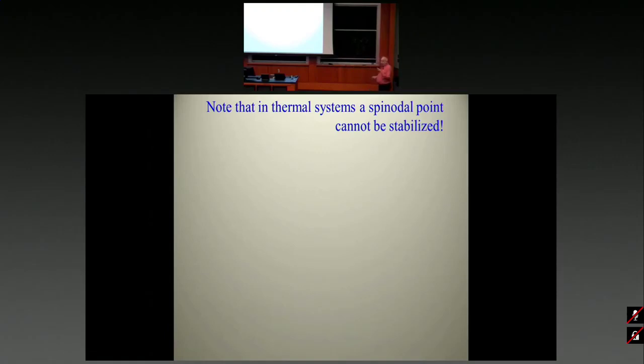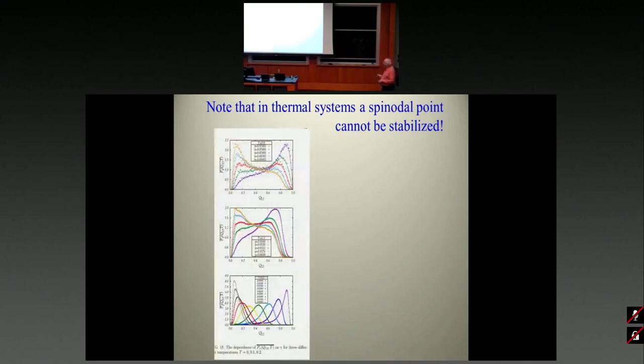So I just want to finish by making the caveat that if you have thermal systems, then things can go berserk. For example, this is just a copy of what I showed before, the 0 temperature. At the temperature of 0.1, you already see that things become sort of more questionable. The nice point of the phase transition here is a bit smeared, and when the temperature is somewhat higher, 0.2, you lose entirely the phase transition. You get a continuous change, and anyway.